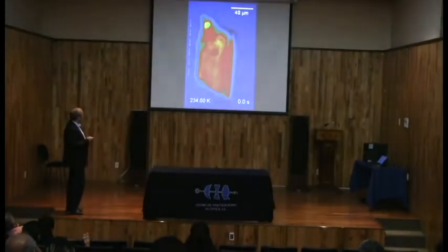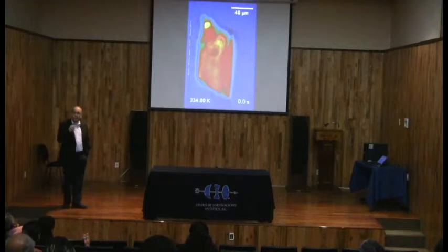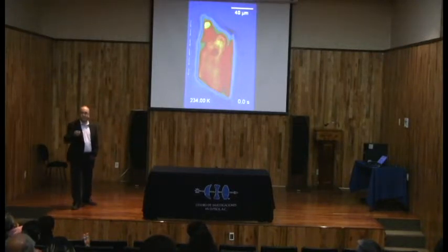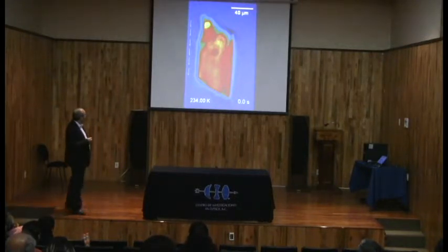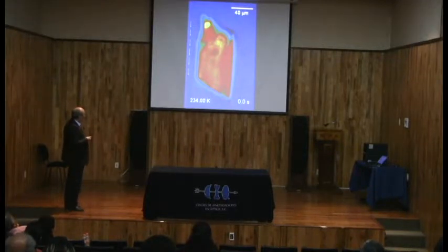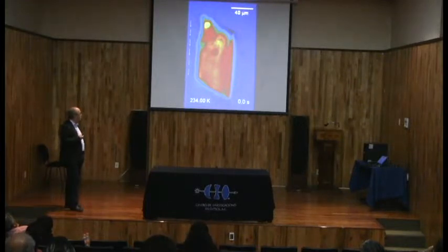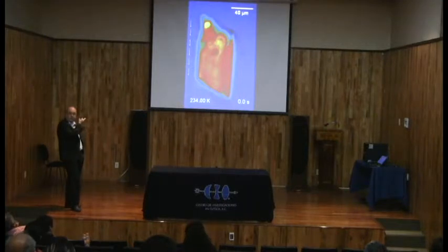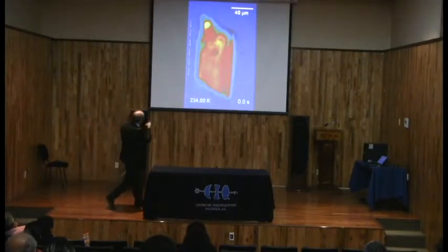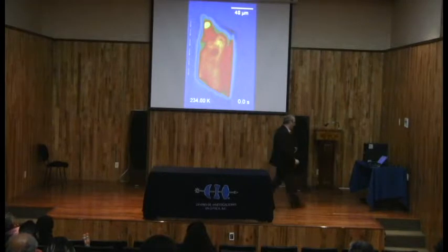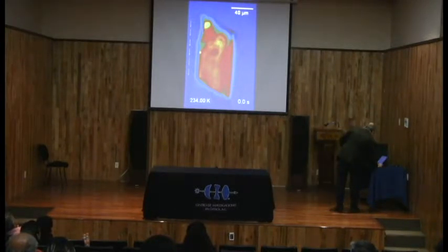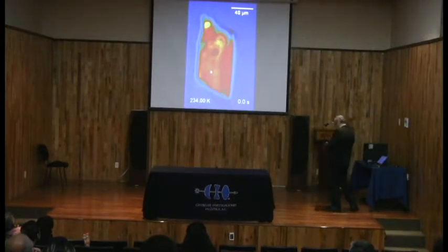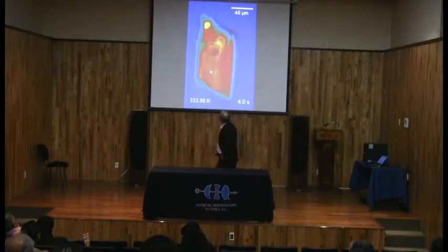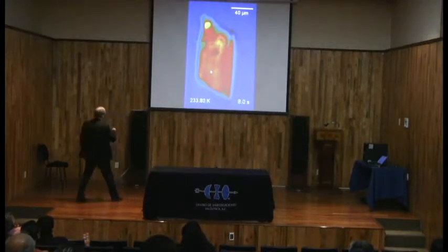Okay. So then we wanted to see it optically, by using polarizers, the crystal through crossed polarizers, and this is the optical experiment through the microscope. We wanted to see this nucleation and growth optically. So you see, this is the crystal. If we increase the temperature, you see that we can optically also see that we have the nucleation and growth.